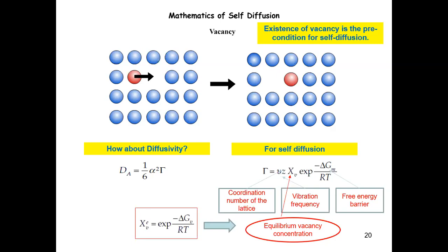But if you have a vacancy, how many configurations can you have for this one vacancy? We have a lot of configurations. If you have an n-atom system, you have n configurations, right? Because any atom can be a vacancy. And you can see that this increases factorially fast if the number of vacancies increases. Does that make sense?